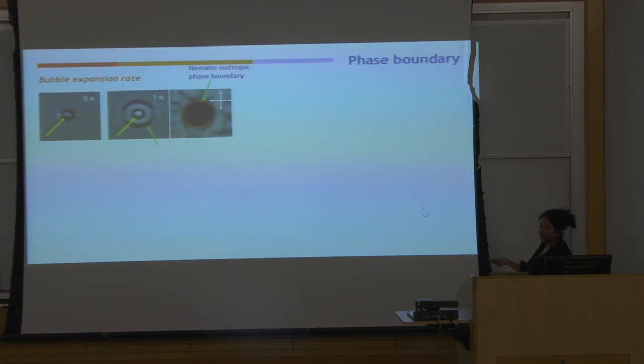And finally, as part of the physics talks, I get to talk about some equations. This is the shell here. In about 1 second, this was the shell, and we saw this thing forming. This is the bubble that forms because this gold shell here is heating the medium, the liquid crystal around here. So the liquid crystal was in the nematic phase. The heat makes this part here become isotropic. When we look at it under cross polarizers, we can see that. This region appears black, while the rest of it remains ordered. So it's creating this phase boundary by heating. That's what that outer ring was. And we can use that to actually calculate how much heat we are producing near here. Because ultimately, if we want to put that near cells, you want to know how much heat that's going to produce, how many cells it will kill, how far.